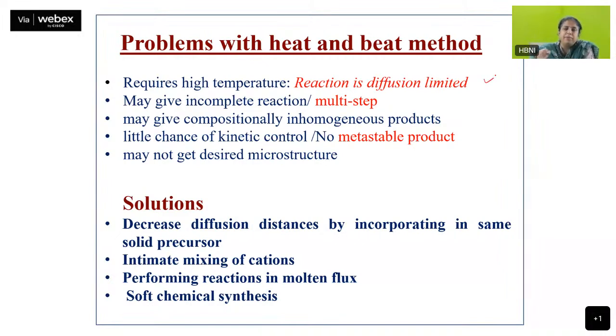It requires high temperature because the reaction is diffusion limited. It may give an incomplete reaction, and that is why you have to do it multi-step. It may give a compositionally inhomogeneous product also if you have not carefully ground your material or done your multi-step heating. And there is little chance of kinetic control. So metastable products by solid state are rather difficult to obtain. And you will not get the desired microstructure because you're heating it to very high temperature. The particles will grow, unless you're using the spark method.